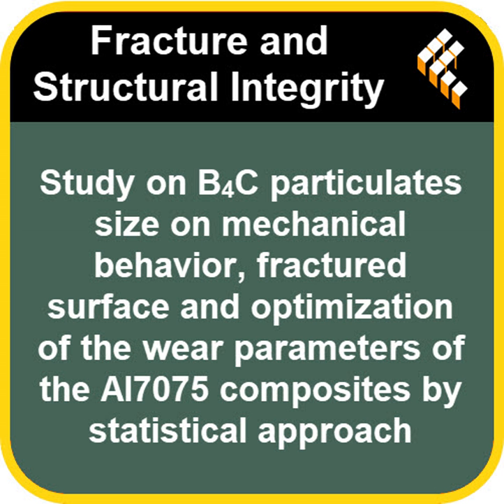Okay, let's switch gears slightly and dive deeper into wear. How things hold up against rubbing and friction. How did they test that? They used a standard piece of lab equipment called a pin-on-disc tribometer. Basically, you take a pin made of your composite material, press it against a rotating steel disc with a constant force, and measure how much material wears away from the pin over time, usually by weight loss. Okay. Standard wear test. And what factors did they vary? They focused on three key things. First, particle size, obviously micro or nano. Second, the sliding speed, how fast the disc was spinning. And third, the sliding distance, how long the test ran for.